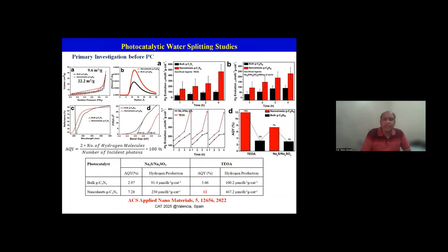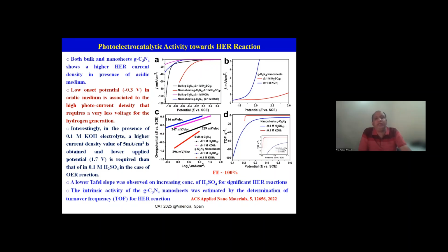Before going to the HER business, we should do the primary investigations like X-ray diffraction, the BET surface area investigation, UV-DRS for optical band gap, PL, TRPL, and the XPS investigation. Then for the hydrogen evolution reaction and photochemical water splitting, we have made two sets of reactions. In one set, we have taken triethanolamine as the sacrificial agent, and in another set, we have taken the combination of sodium sulfide and sodium sulfite. We observed that triethanolamine as the sacrificial agent is able to produce 470 micromole per hour per gram of hydrogen with an apparent quantum yield of 12%, whereas the sodium sulfide sacrificial agent is able to produce 230 micromole per hour per gram of hydrogen with an apparent quantum yield of 7%.